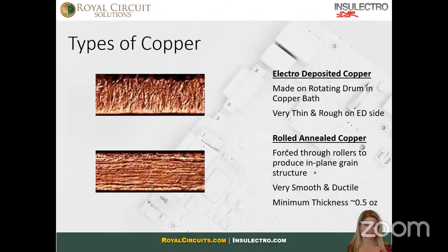To make the copper more durable, manufacturers will take thick sheets of ED foil and feed it through giant hydraulic roller presses. That serves two purposes. First, it thins the copper out, makes it smooth and ductile. And now it's oriented parallel to the plane, still like the trees in the forest, but they're long and slender, but now the trees are cut down and pointing in a single direction. Unfortunately, copper has the tendency to harden during processing. So foil manufacturers anneal the copper foil by heating it up, cooling it down. The result is the copper is thin, pliable, and easy for fabricators to work with.